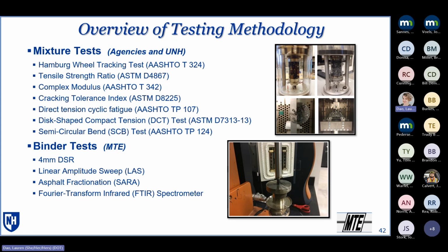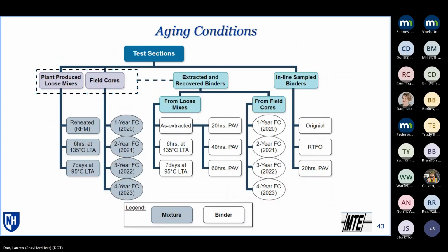Now, it wasn't just the plant produced material. We did a whole bunch of different aging conditions. So very comprehensive work in terms of the data that we've collected here. For each of the test sections, we've got the plant produced loose mix, and that plant produced loose mix we tested in the reheated condition, 6 hours at 135 degrees C, long-term aging, which was what was determined at the beginning of the project as one long-term aging condition.